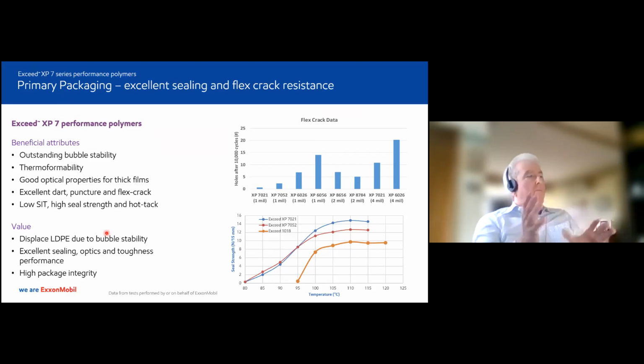Now I'll switch briefly over to some primary packaging, because some of you would have seen that low density and thought, boy, that's a good grade I can use in some primary packaging applications. And the particular property that I want to raise here is the flex crack resistance. It really is outstanding. You can see along the x-axis here that the 7 series, these 2 grades here, have particularly low hole formation even after 10,000 cycles on the flex crack test, which is now approaching and perhaps even bettering some of the XP8 series, which is our other very good series for flex crack.